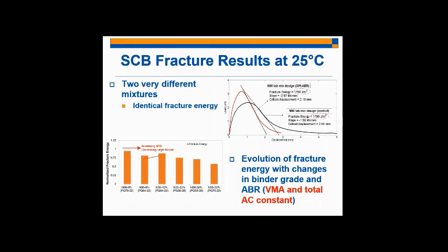And so we move on to the shortcoming that we have basically with the 25 degrees Celsius. So we've kind of addressed the shortcoming in the low temperature testing condition. Now we're faced with another shortcoming, and that is basically that the fracture energy is not a sufficient criteria to distinguish between mixes on its own.